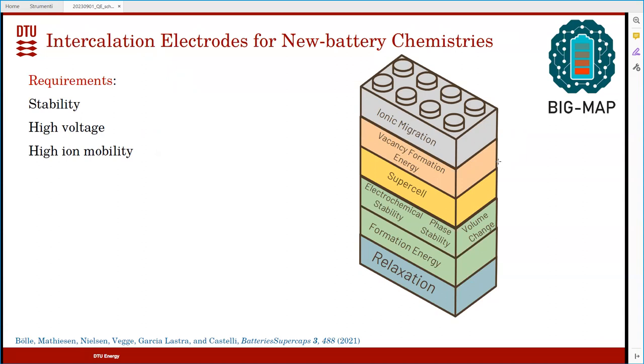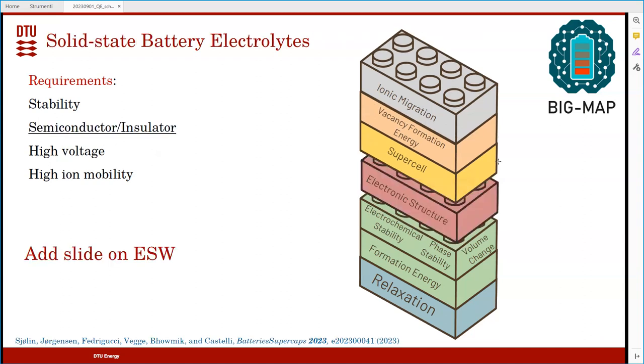So this is something we've done, as I showed you, for new battery chemistries. We do relaxation, we calculate formation energy, chemical stability, phase stability, volume change. Then we build a supercell and compute the vacancy formation energy to get to the open circuit voltage, and then migration to get to the diffusion. So this was what I showed you.